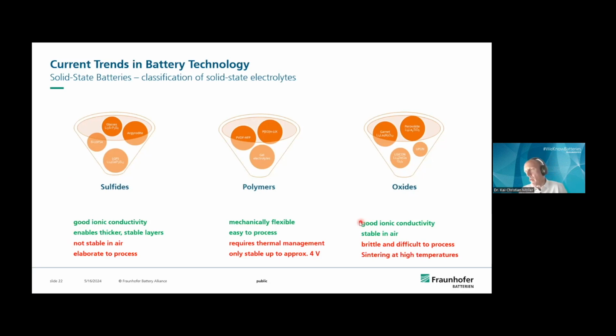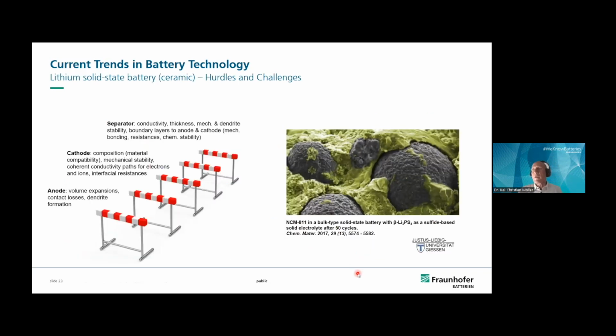And then there are oxidic ionic conductors. They are stable in air. They are already oxidized, but they are very brittle and difficult to process. And to make the electrodes, you need sintering at high temperatures. And one of these electrodes you can see here in this electron microscope picture. You see the particles of the active material and the electrolyte in green. It's a big difficulty to make these compounds with a good contact.